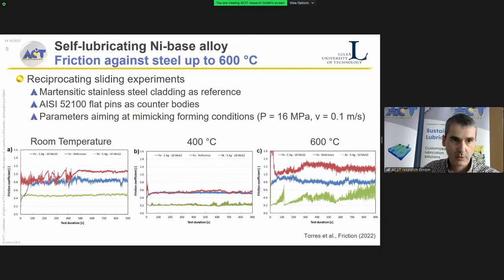And we can see here that when we use the martensitic stainless steel, friction is very high. And when we use, for example, the nickel-based alloy, the green lines, we are able to have a very steady and low friction. For example, look here at 400 degrees, we can have a metal-to-metal contact at 400 degrees without any lubricant and a steady coefficient of friction of 0.2 compared to close to 0.6 for the martensitic stainless steel. So very good friction performance, and at 600 degrees still managed to get some good performance, much better than the reference alloy, but already struggles a bit.